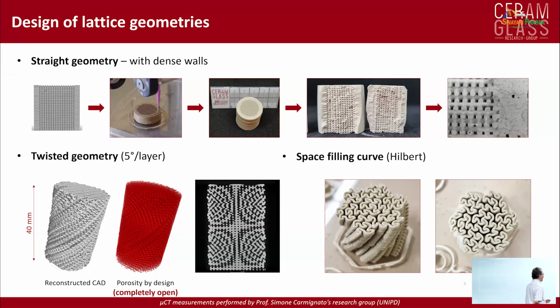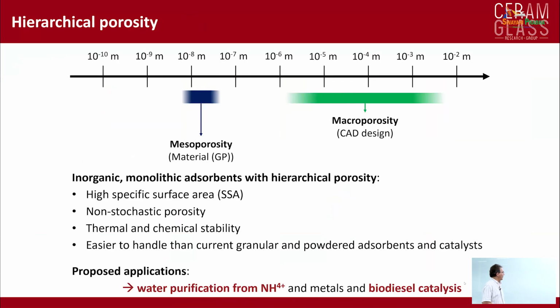And you can see here a tomography reconstruction of a structure. In this case, it was not a space filling curve, but it was based on twisted scaffolds, and you can see the complex porosity inside that can be optimized for providing, for instance, mixing of different fluids. So on one side, using additive manufacturing, we can manipulate the macro porosity at any level, meaning that we can modify the amount of macro porosity, we can modify the size of the macro porosity, we can modify the geometry of the macro porosity. But we are interested in functional components where a fluid interacts with a solid material.